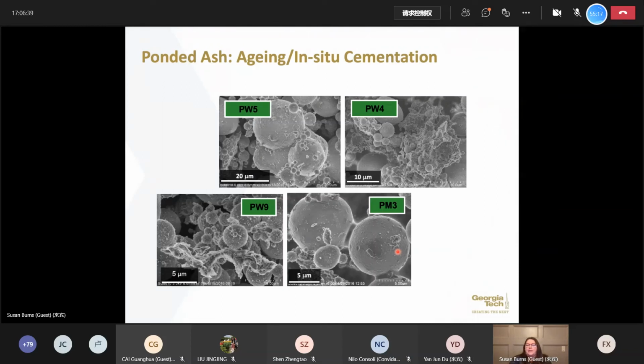I want to circle back now to some SEM images to take a little bit deeper look at what we have in terms of aging and in situ cementation. So these are ponded fly ashes. All of these samples that you see here are the ashes which have been aged for about 10 years or less. And what you see is changes in the morphology.